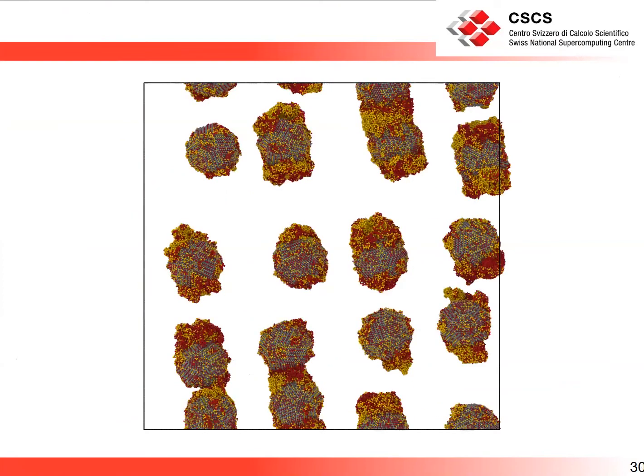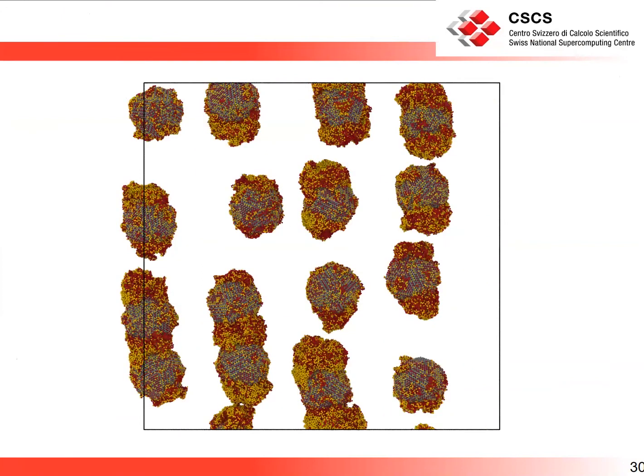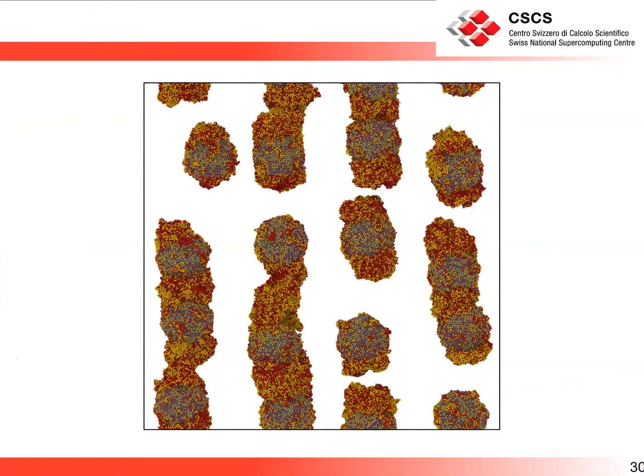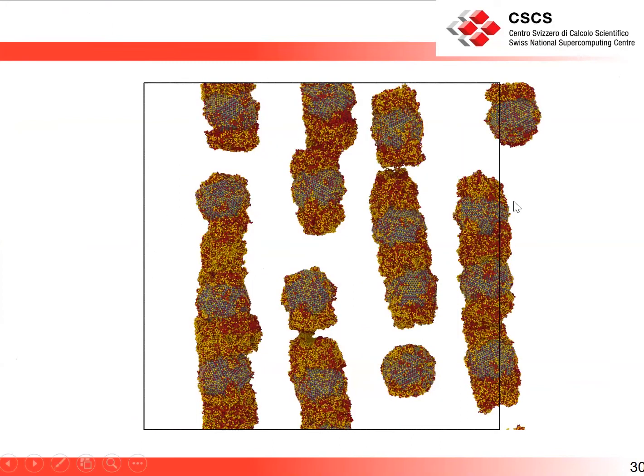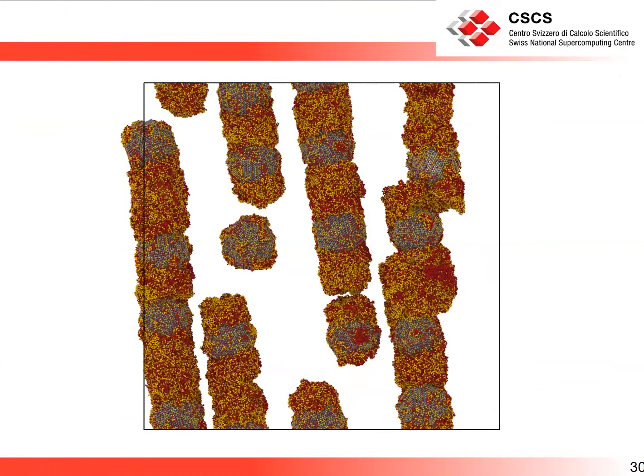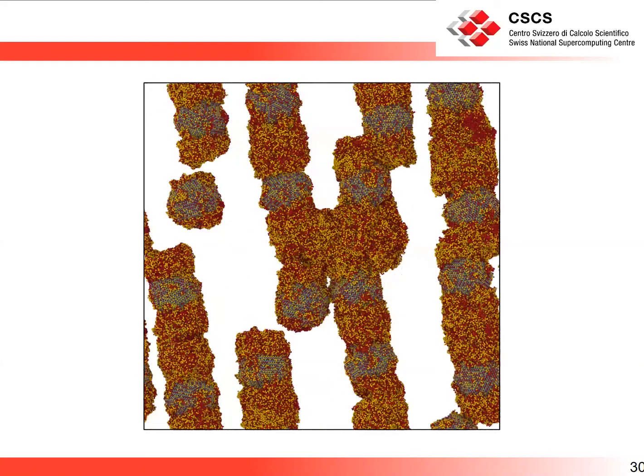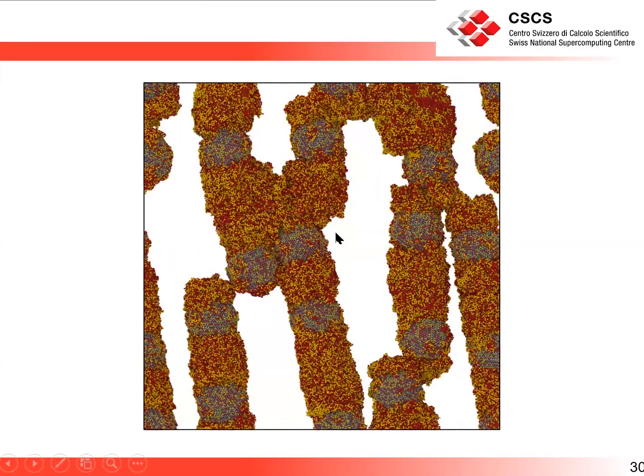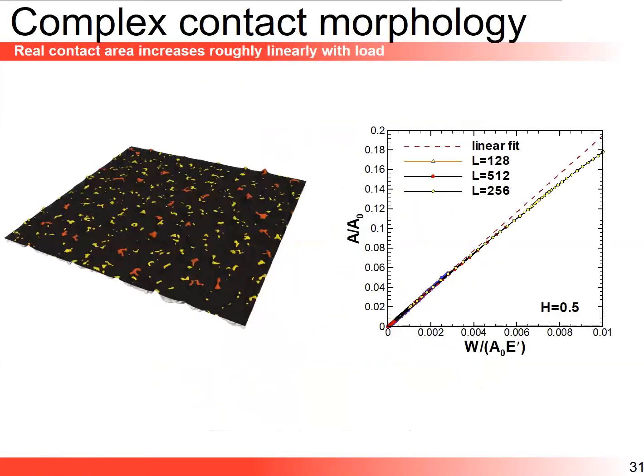So the molecular dynamics simulations again. You see the accumulated mass, they grow in length, they become like French baguettes, if you want. They start to attach to each other, and you can tell the sliding direction is left to right, at a slight angle. And as they attach, they elongate in one direction. They also start to attach on a side, and this has important consequences on the emerging frictional properties of the system.